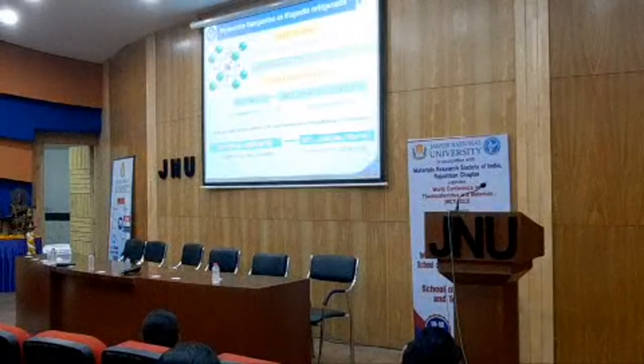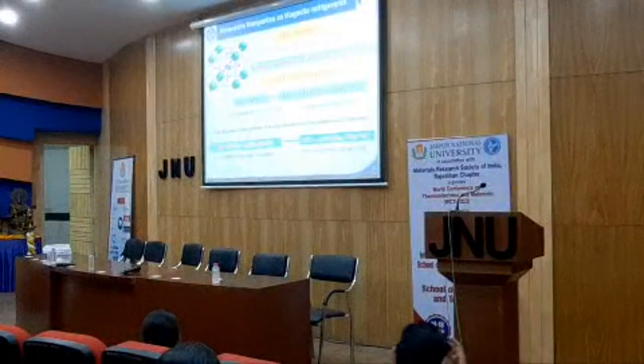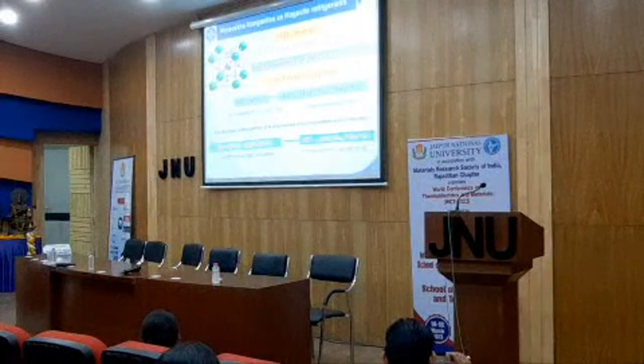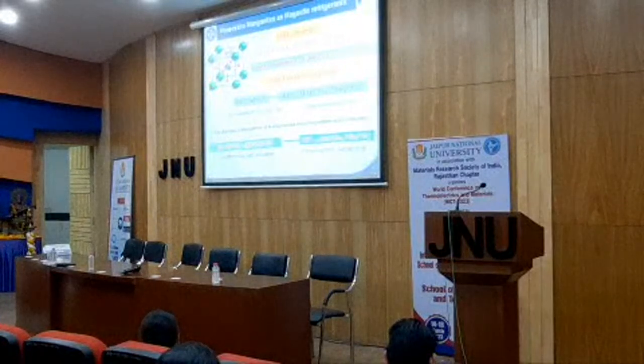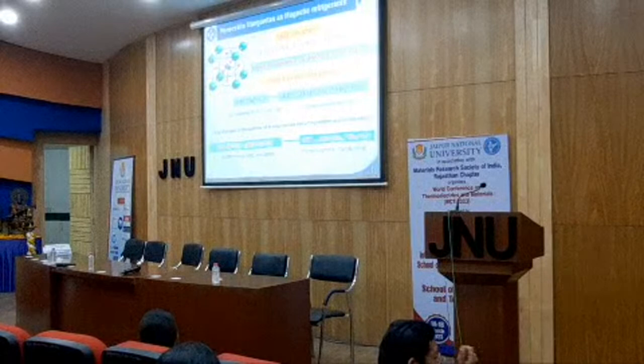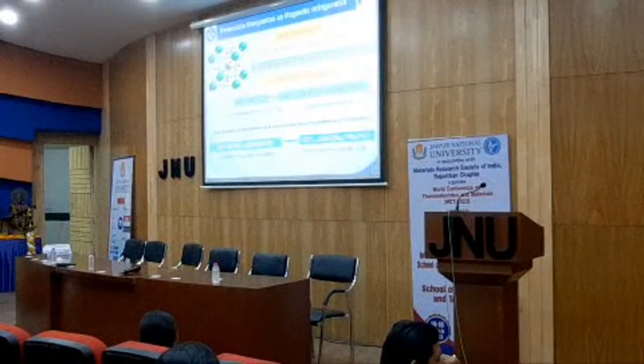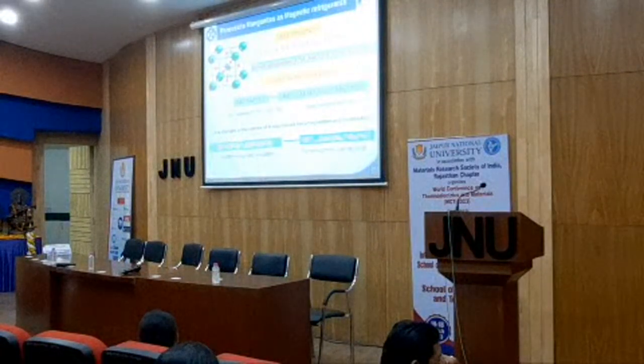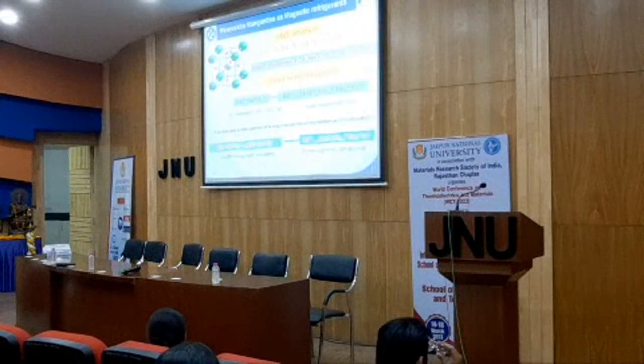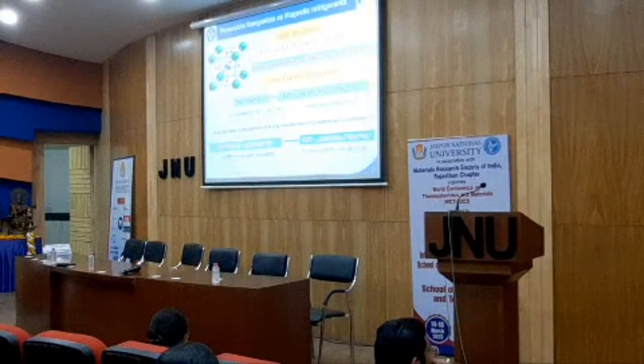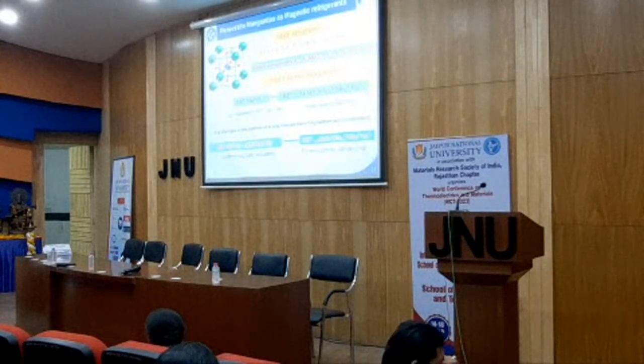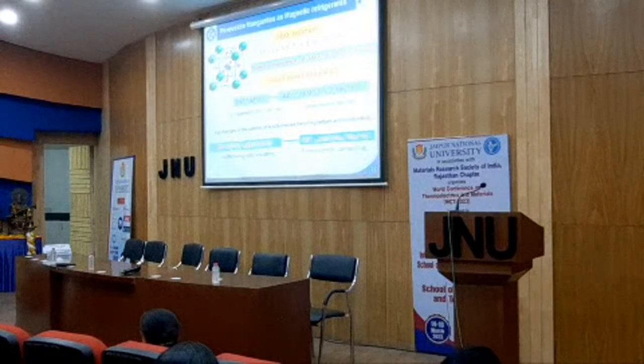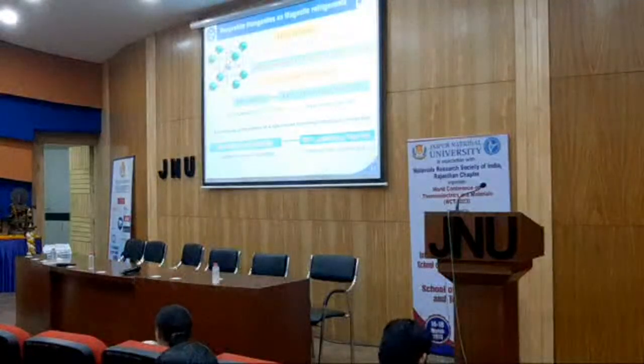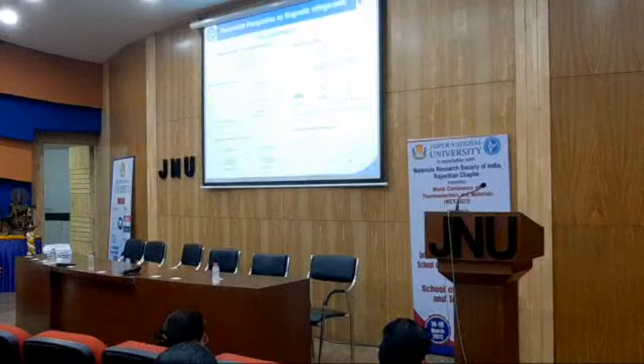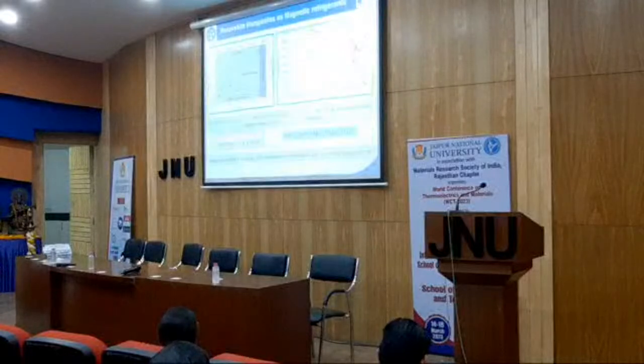So here, the parent compound, I am just showing the same formula, one end to another end, properties are there in terms of magnetic and transport properties. Magnetically, these compounds are mostly antiferromagnetic and highly insulating materials. But a little substitution of these alkaline materials turns this material ferromagnetic. It is strongly conductive. Time is over. I'll finish it. Okay. Next, please.